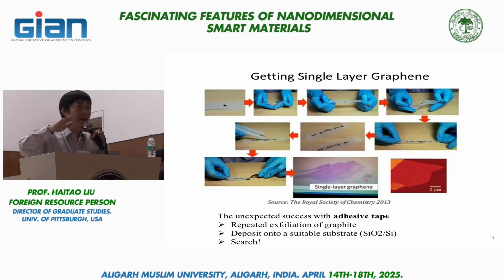Okay. And then what happens after is to some degree scientific, to some degree religious, because you have to massage it in some special way. Every scientist has a different way of massaging the surface. And somehow, some of those thin flakes got transferred from that tape to the silicon wafer. And miraculously, you can get single-layer graphene this way. It's very counterintuitive, but it worked very well.